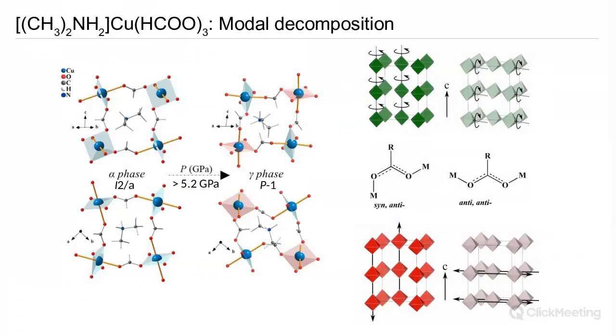So the way we interpret these results is to say that we take the observation that this phase transition has not occurred in the inorganic system, but it has occurred in the hybrid organic-inorganic system. We infer then that the reason this transition can occur is because these unconventional structural distortions are allowed in the hybrid organic-inorganic system where they were not in the inorganic. But we can actually look slightly closer at the problem and what the implications are of these unconventional modes with regards to the bonding to the formate. And just by observation, a lot of the perovskites of this structural form have formate bonded in anti-anti fashion, which I've drawn on the right-hand side of the figure here.